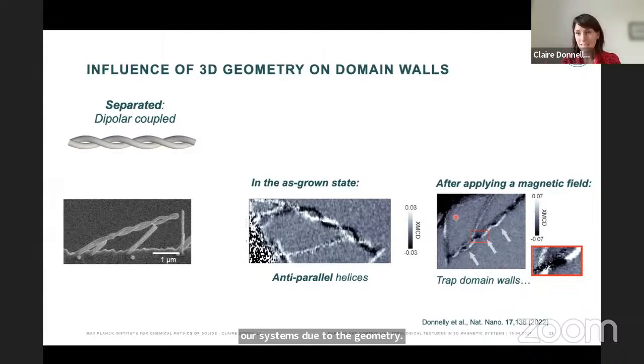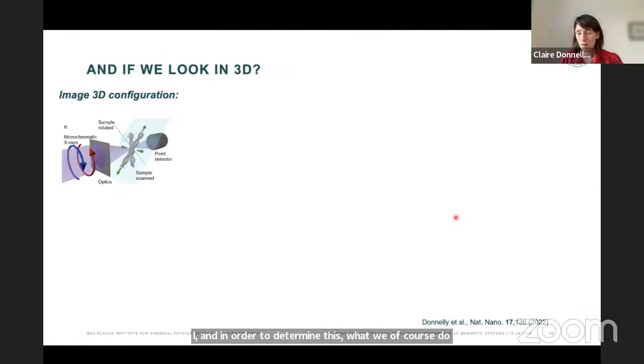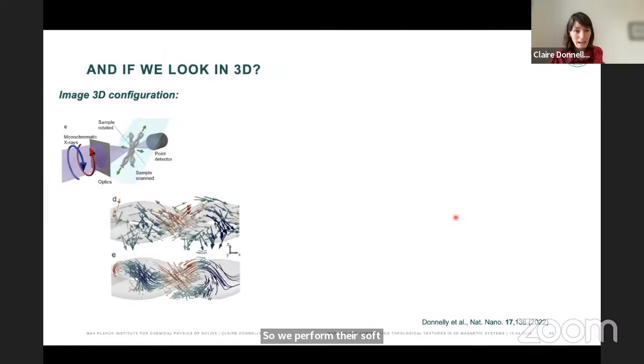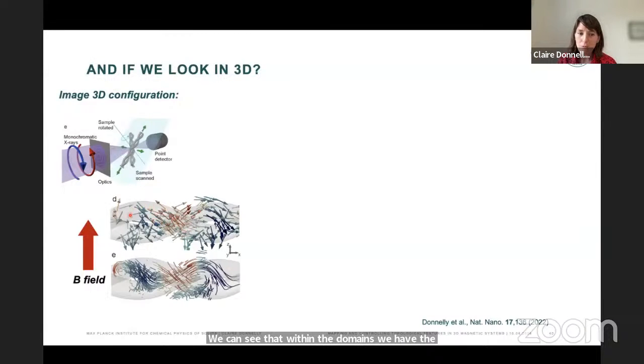The question that we were asking ourselves was, what effect does this three-dimensional geometry of our double helix structure have on the domain walls? In order to determine this, we perform our 3D magnetic imaging, soft X-ray magnetic laminography, and with that, we're able to resolve the magnetic configuration within these double helices. What's particularly interesting here is that if we consider the direction of the magnetic field that was applied, we can see that within the domains, the magnetization is generally pointing parallel to the magnetic field, but within the domain walls, the magnetization is pointing anti-parallel.